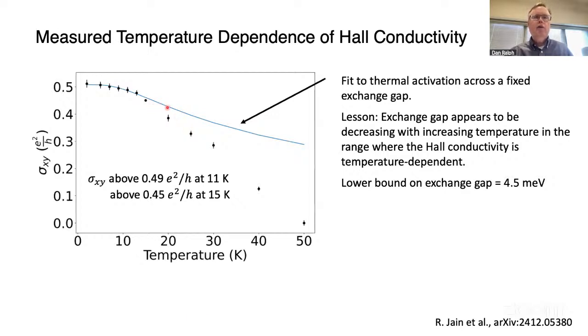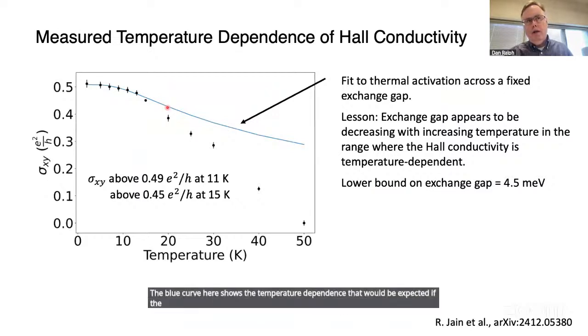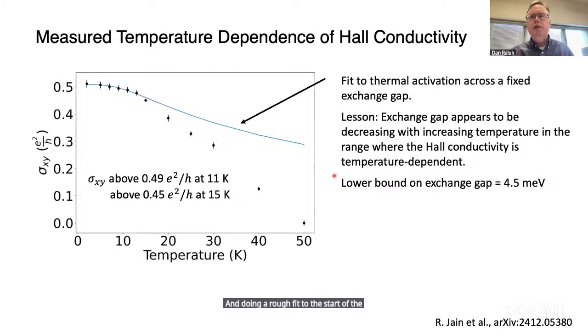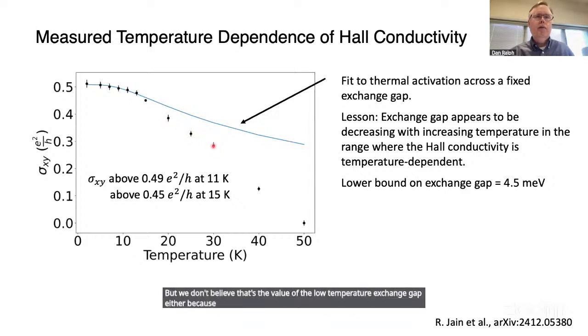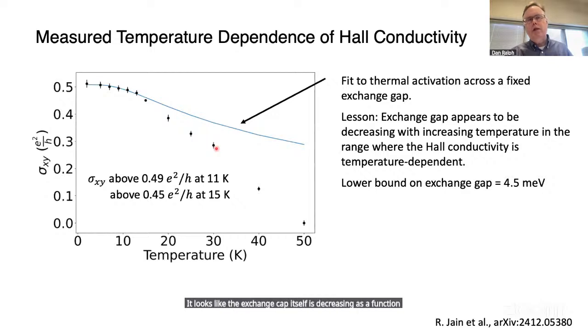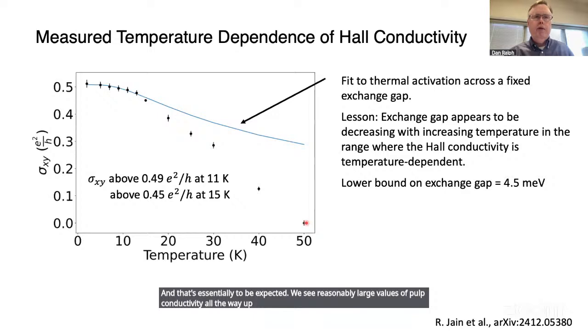The blue curve here shows the temperature dependence that would be expected if the exchange gap itself did not depend on temperature. And doing a rough fit to the start of the temperature dependence here at low temperatures gives a lower bound on the exchange gap, about 4.5 millielectron volts. But we don't believe that's the value of the low temperature exchange gap either, because as we see over this temperature range, it looks like the exchange gap itself is decreasing as we go up in temperature, and that's essentially to be expected. We see reasonably large values of Hall conductivity all the way up to near the Curie temperature of the chromium germanium telluride, which is 50 or 60 Kelvin.